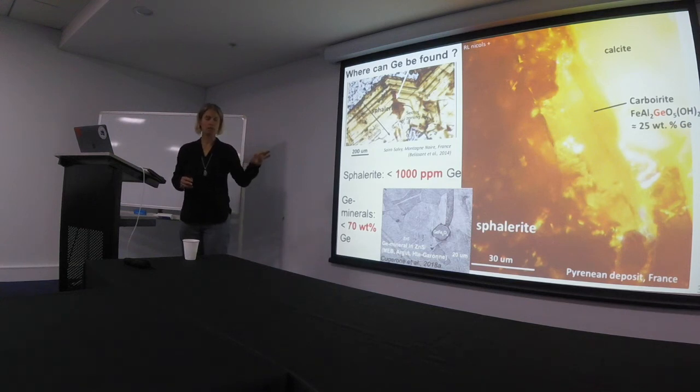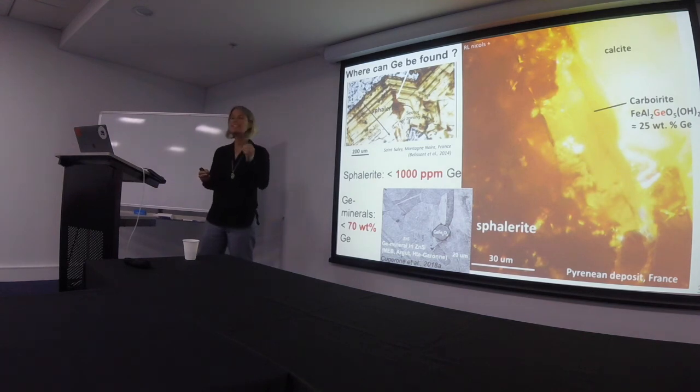We've considered having a depleted sphalerite with only maybe 0.01 volume percent of these germanium minerals, and we have distributed it back into the sphalerite in the same volume. We ended up with a few hundreds of ppm in the sphalerite lattice. So in the end, I think this redistribution happens at such a small scale that we just don't see it.